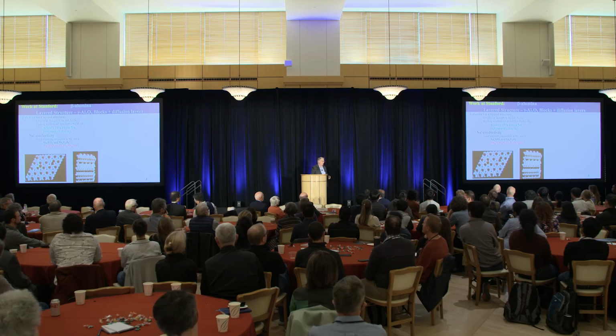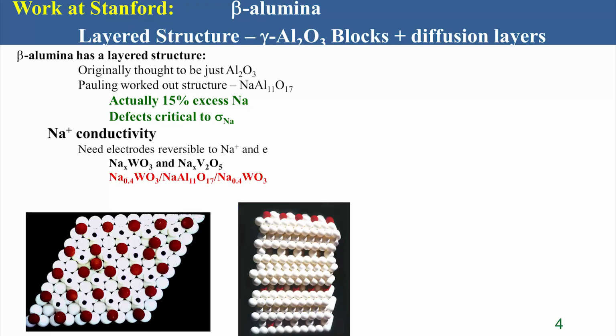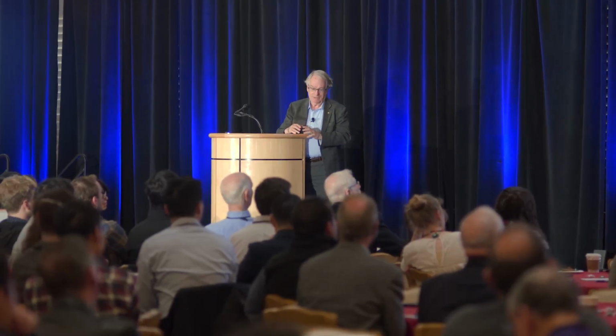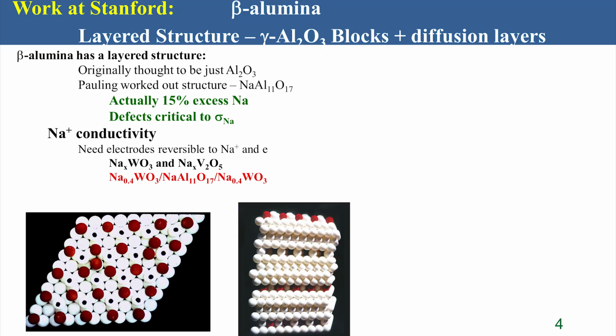So let me just say a little bit of what we did here. In 1967, Ford Motor Company published a paper on this compound called beta alumina. They claimed the sodium ions moved just as fast in the solid as they did in aqueous solutions. And it's called beta alumina because it's thought to be just another polymorph of aluminum oxide, but it was Linus Pauling who said, no, this is a layered structure, and I show you at the bottom here. And it's gamma alumina blocks with these very open structures where the ions can very readily move in there.